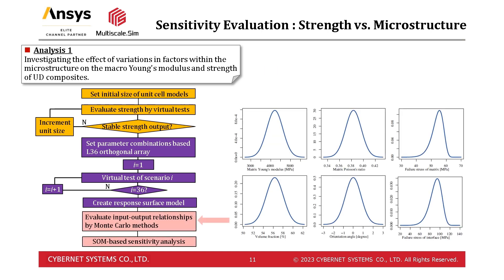This means we created a reduced-order model for determining the relationship between microstructural variation factors and material properties. The last step was to use this reduced-order model to investigate the relationship between a large number of combinations of variation factors and material properties. The degree of variability was defined using the Weibull distribution for the strength factor and Gaussian distribution for the other factors, based on actual measurements made on several specimens. Since the analysis model has six variation factors, the self-organized map, or SOM, was used to visualize the correlation between inputs and outputs.